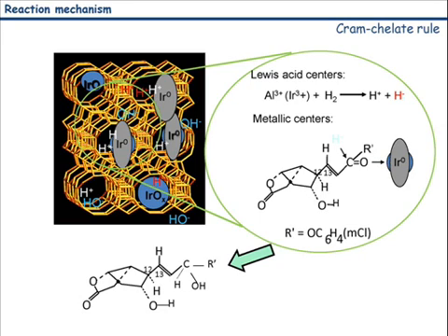Now, why? You have to calcine the zeolite, because when you calcine the zeolite, it is proved by NMR that you induce in addition some penta-coordinated aluminum, and this favors the formation of iridium oxidized basic species. So based on this measurement, we propose